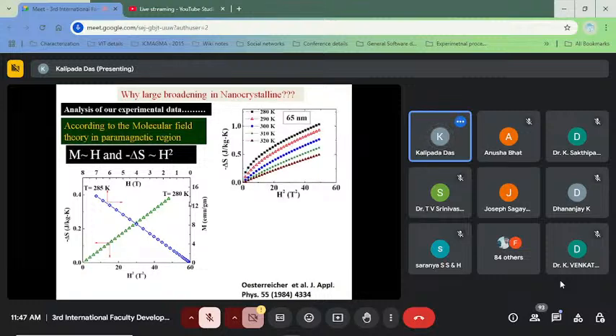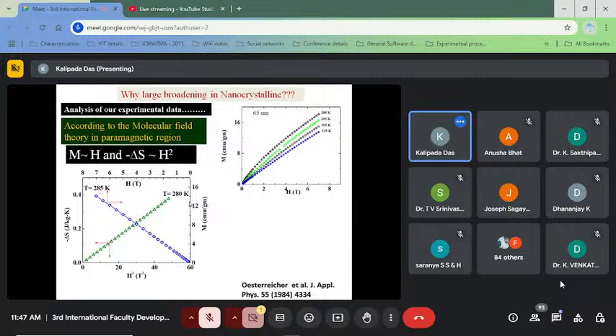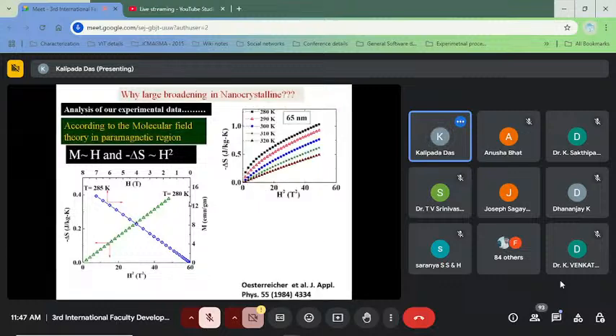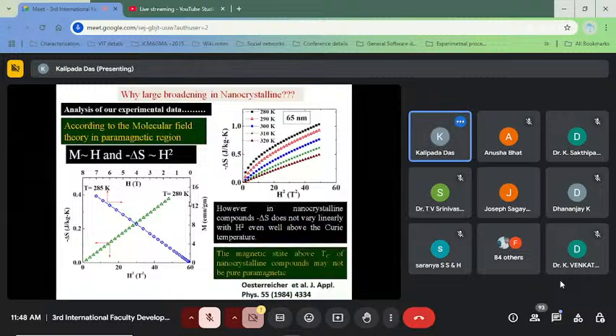However, in the case of nanomaterials, the M versus H is not linear, even above the ordering temperature. Similarly, minus delta S, that means magnetocaloric entropy change, versus H squared is not linear, but it should be linear in the paramagnetic region. But in the case of the nanomaterial, it is somewhat curved. Such curvature may appear if, in the paramagnetic state, there are some ferromagnetic type nano clusters.